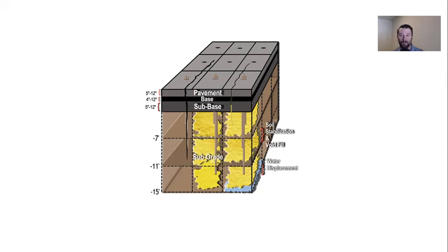For those who aren't familiar with expanding polyurethane grout, we use a two-part polyurethane foaming system. So it starts out as two liquid components. When introduced to one another, the reaction between those components is an expansion. The material used for this project had the opportunity to permeate through more granular soils first, and then as it started to expand, that expansion is what would cause the displacement, compaction, further densification of the embankment here.